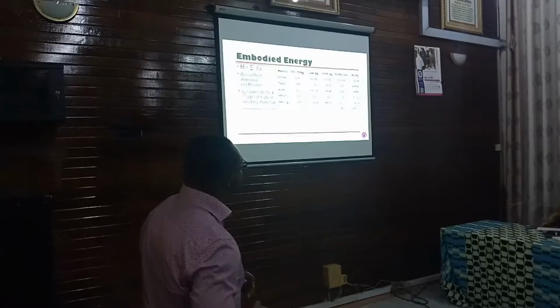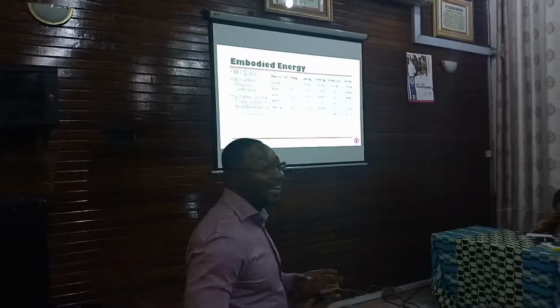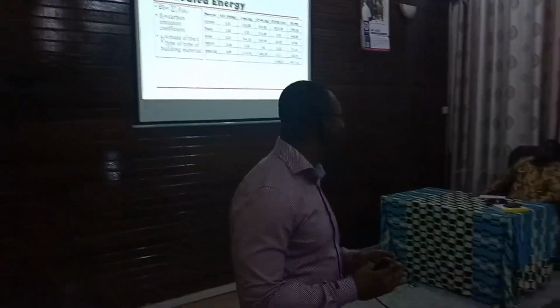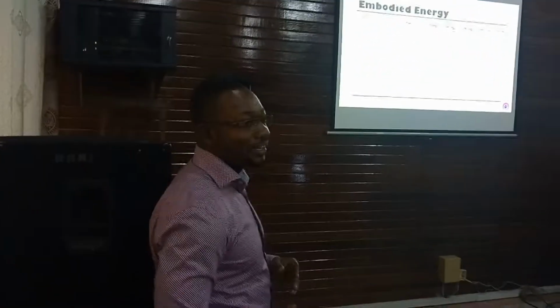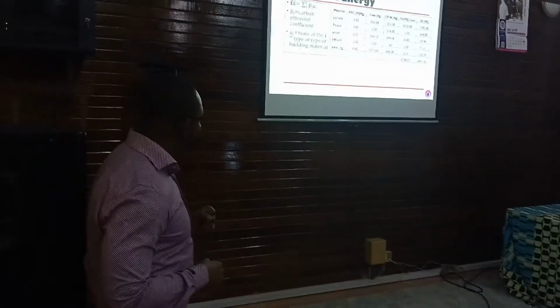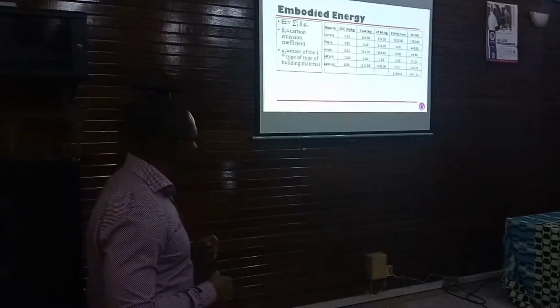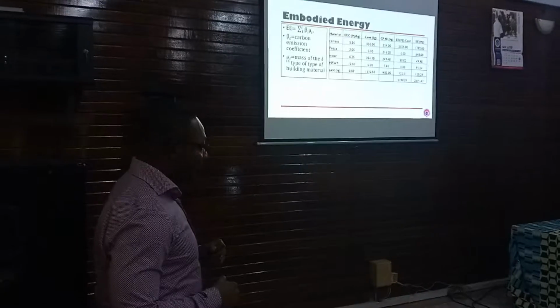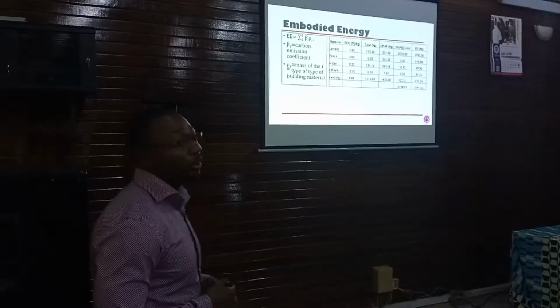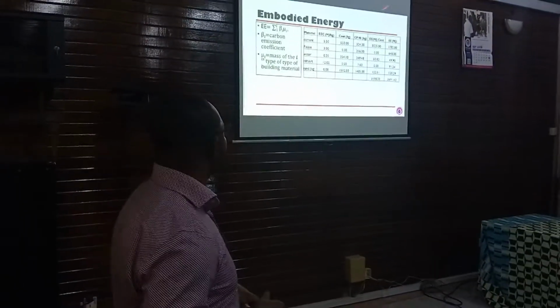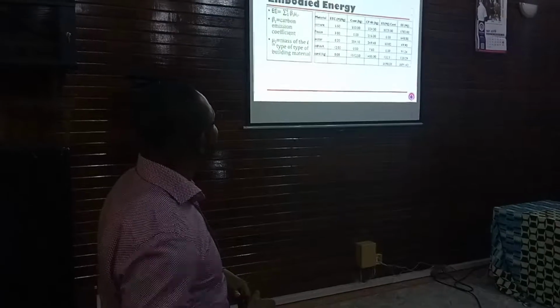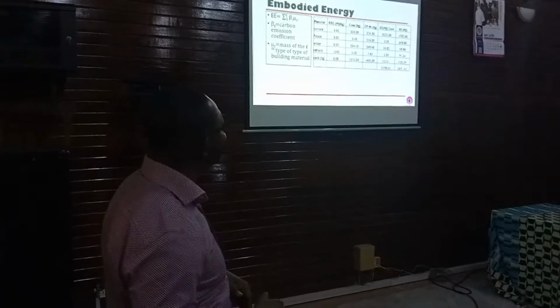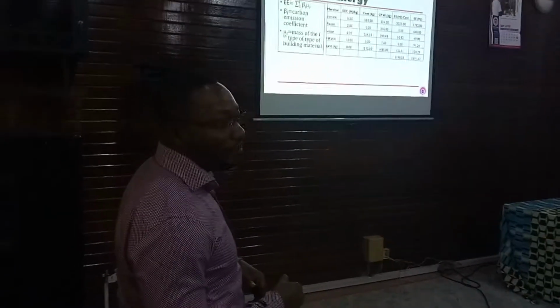Now when we come to pozzolan, the embodied energy of clay, baking of clay, is 3.0 megajoules per kilogram. The embodied energy of water is 0.2 megajoules per kilogram. And then the embodied energy of the chemical admixture, that is the high range water reducer, is about 12.0 megajoules per kilogram.